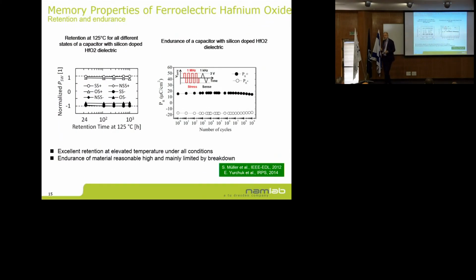Then we checked reliability, and in ferroelectrics you have to be a little bit careful with retention because there is the so-called imprint effect. A ferroelectric tends to stabilize the polarization state it's stored in. Now, if after retention you reprogram the cell, then all of a sudden the other state will be unstable. So you have to measure also the retention of the other state. That's why you see so many curves here. But it turns out that if you optimize the material, you get stable polarization in all states. And cycling is going up to 10^9, 10^10 cycles.